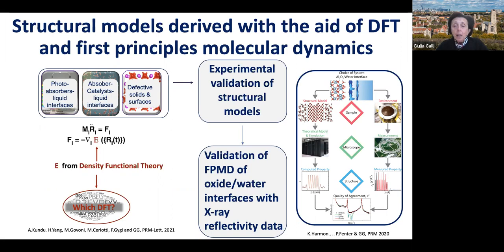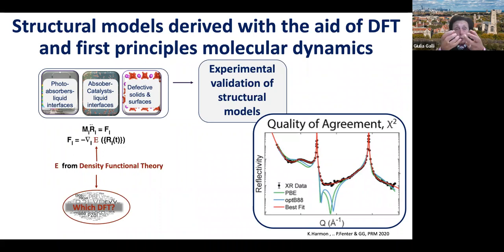we picked a specific surface. Actually, this was supposed to be a simple interface, the alumina, aluminum oxide and water interface, before going to more complex, transition metal oxides, but in itself, it turned out to be quite complex. We set up a model, and we knew the surface termination that they had experimentally. And they did the experiment, and the question was, if we look at the X-ray reflectivity which comes from the interface, do we have something which is in agreement with the experiment telling us that we are doing a good job? And this is what we got for the X-ray reflectivity.